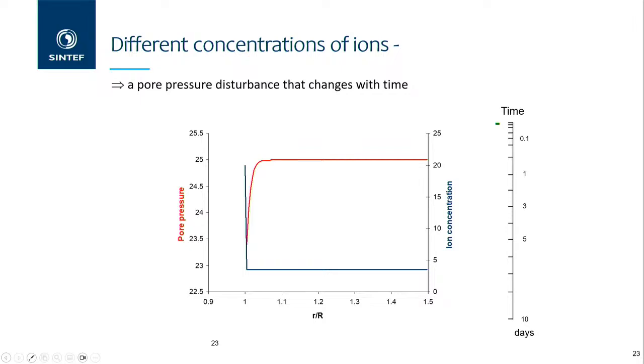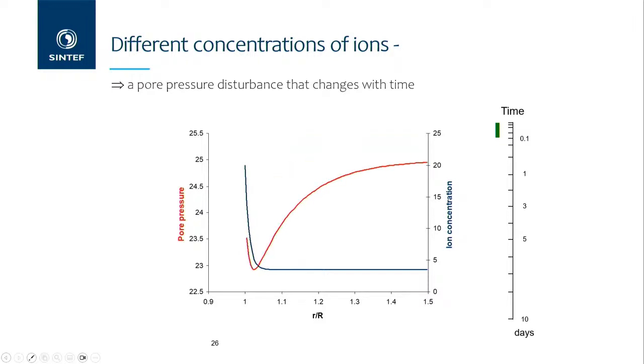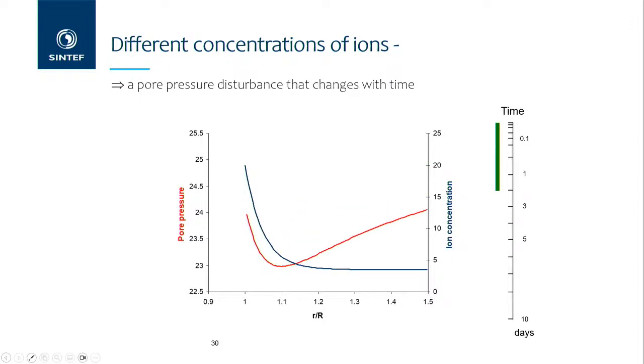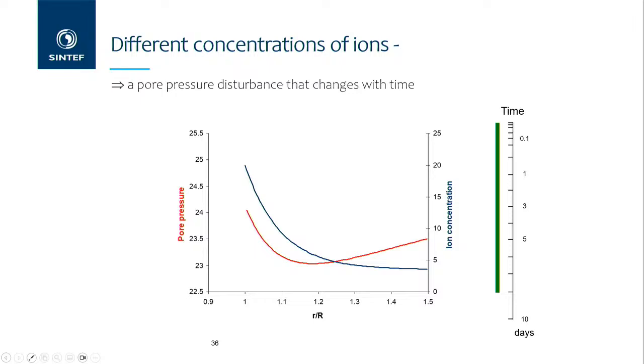Okay, so what happened? Here, this is the borehole. This figure is made by Arling, and he asked me if I want to use it, so I used it. It's easy to visualize. So this is your borehole, and you have a concentration of ion of 20% here, and the shale is 3.5 or 4, and this is pore pressure. In the beginning, you have a drop here because of the well pressure. In this case, the well pressure is a little bit below. What happens when you expose it with time? This is the time axis here. Pressure goes down, and this down pressure settles here and moves in this direction. And then finally it equilibrates.